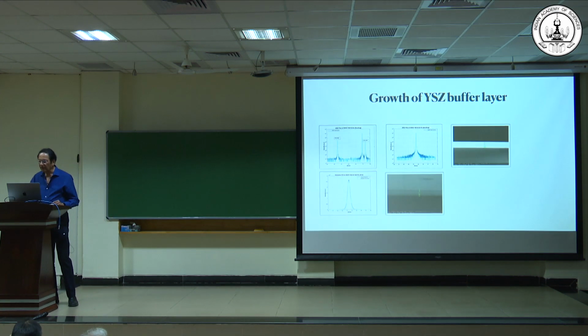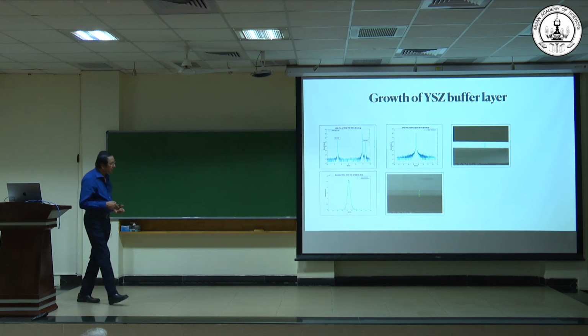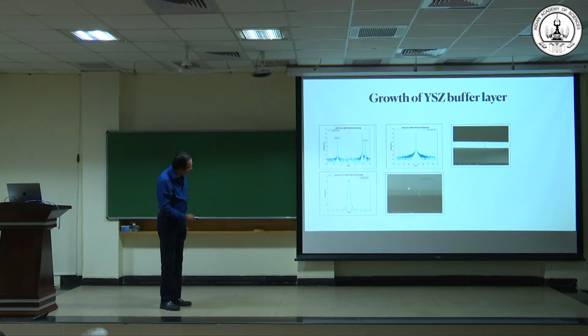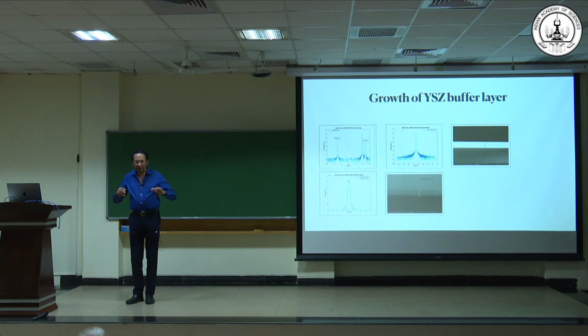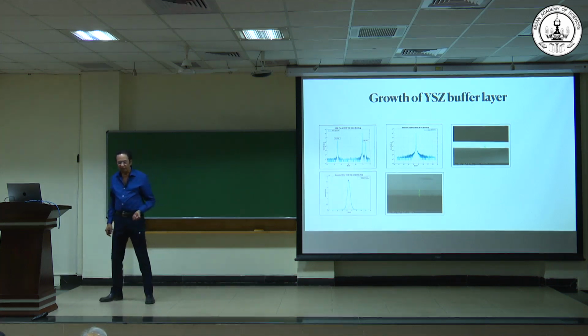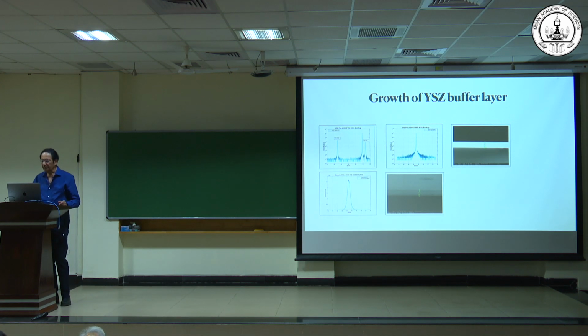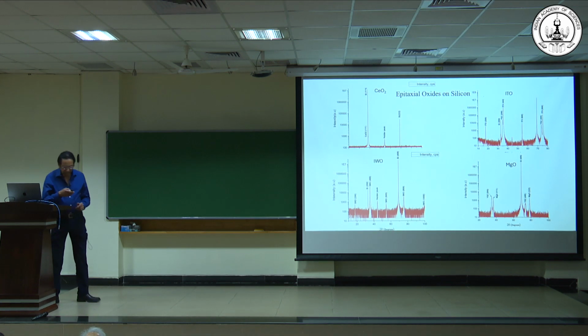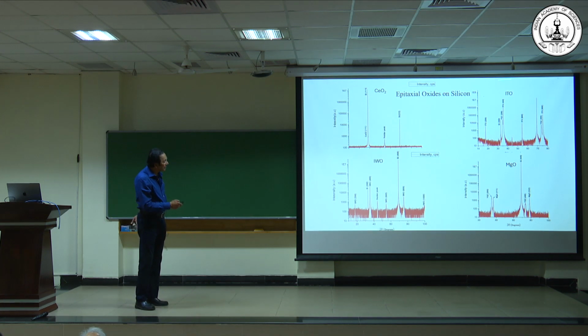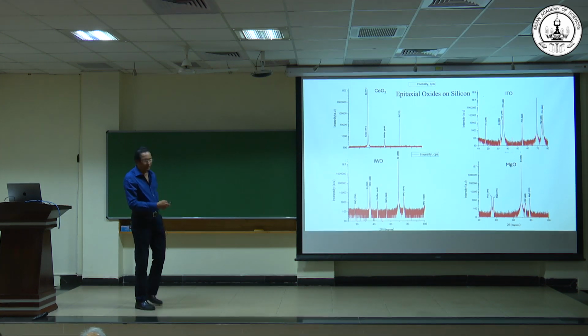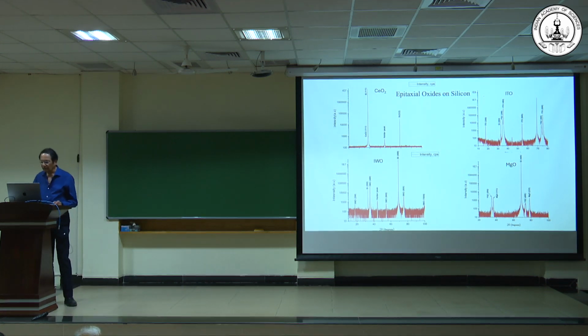So, what we've done is now we have actually shown that this is a yttrium stabilized zirconia film. So, you can see this is the YSZ film that is grown on the silicon, and it is literally a single crystalline film that we're growing right now of this YSZ on silicon. Just starting with the native oxide on silicon, the YSZ has such a strong affinity for oxygen, it just eats up the oxygen and goes to the surface and grows epitaxially. Just an amazing material system. Not only that, we are now growing cerium oxide, indium tin oxide, magnesium oxide, and tungsten doped indium oxide. We're now growing a whole range of different oxides directly on silicon in a crystalline way.